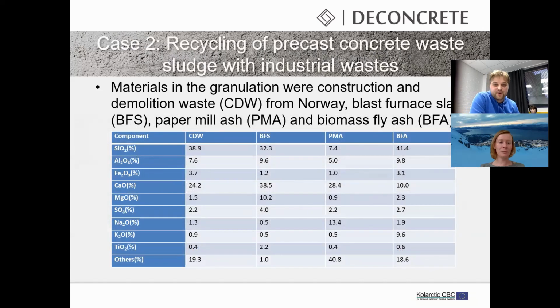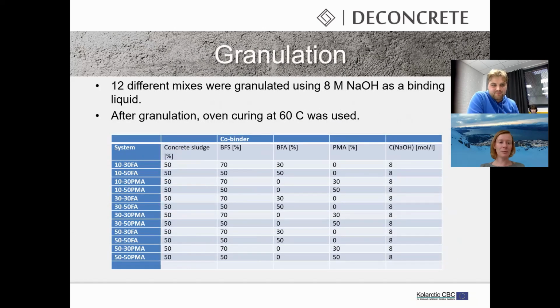And this is my second case. I have used this precast concrete waste from Norway. I think it was mentioned in Iveta's presentation, and also blast furnace slag, paper mill ash and biomass fly ash as co-binders. Here are again the components of those, but again they contain high amounts of aluminum, silicon and calcium. This time I made quite many preliminary experiments before I found a suitable composition for the granules. So I did a total of 12 different mixes, and they always contained blast furnace slag and either paper mill ash or biomass fly ash.